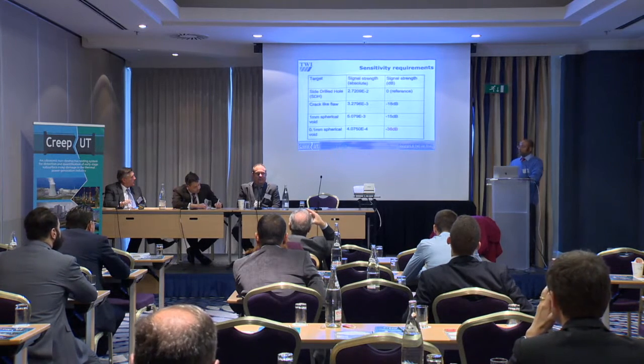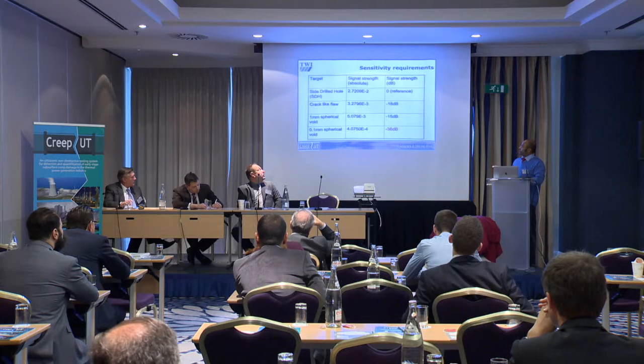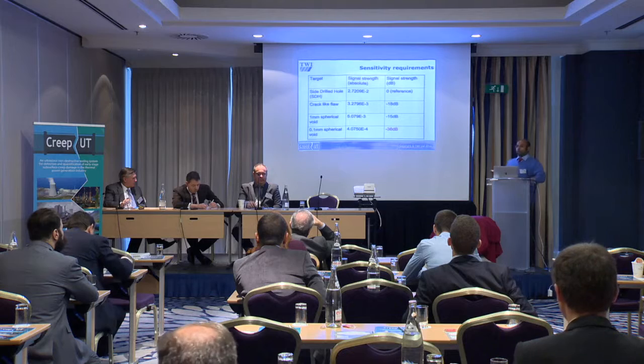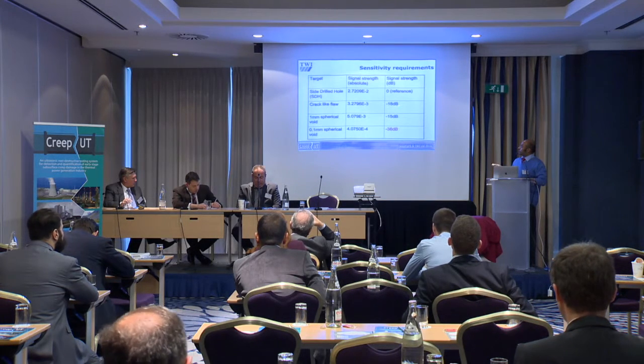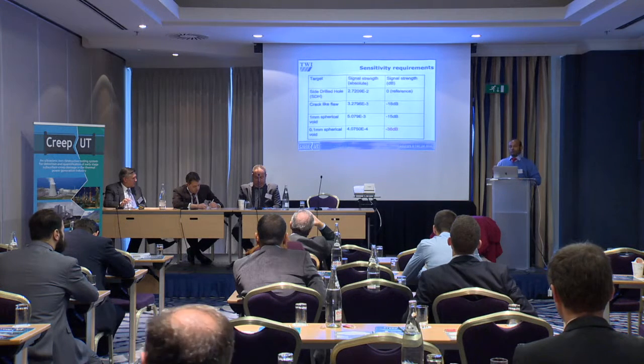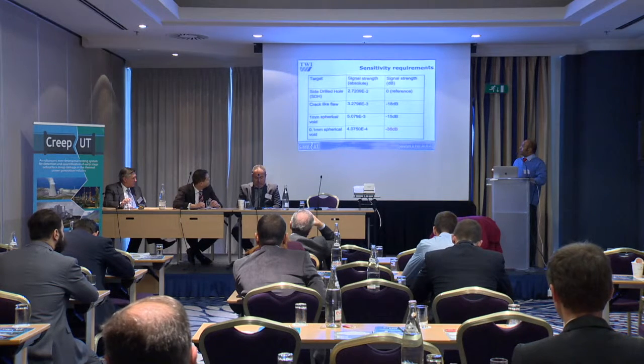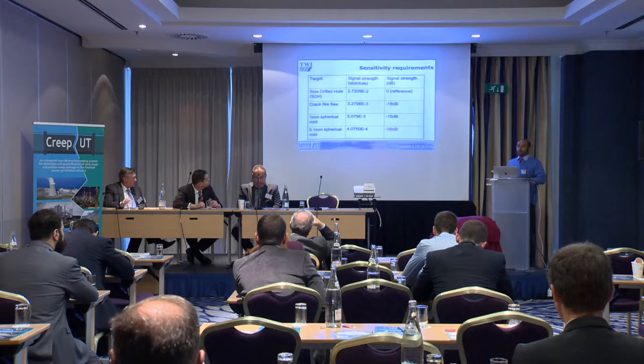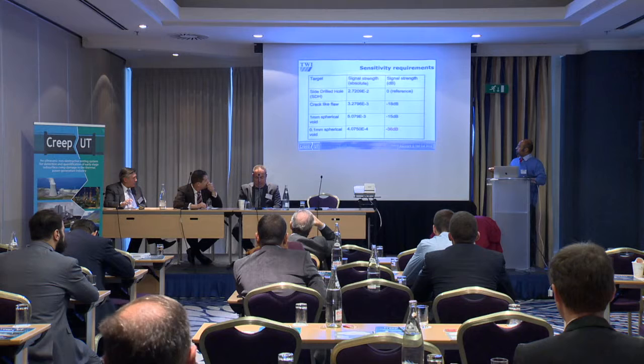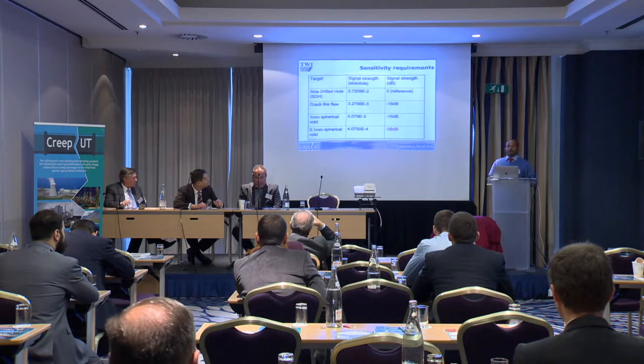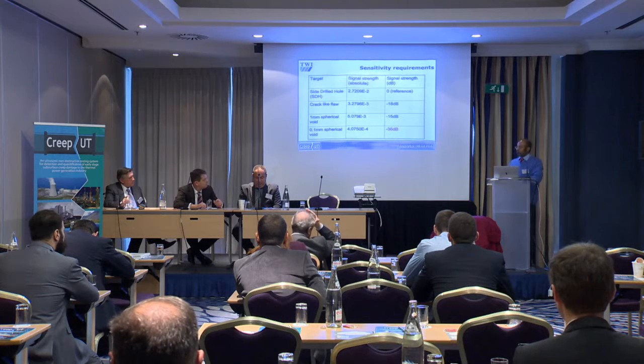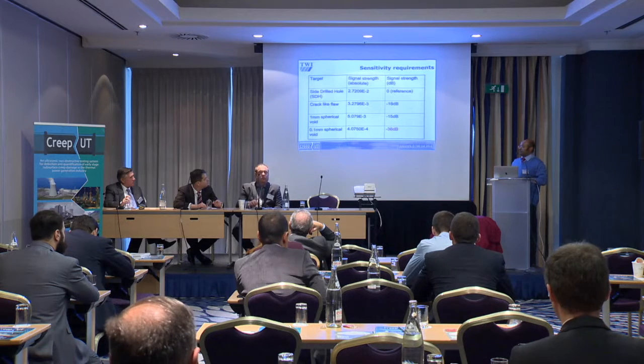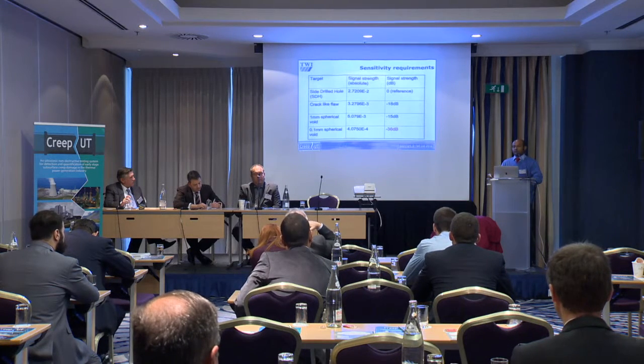And when we did some theoretical assessment at that time, similar to what Marco showed, what you have here is with reference to a standard 3 millimeter side-drilled hole, which is the reference signal. If you look at diffraction from a crack-like flaw, you need to have a system that will be able to give you signal-to-noise performance good enough for something that is 18 decibels below that crack. If you're looking for a 1 millimeter spherical void, such as porosity, then you're looking at 15 decibels down from that. But you can see that if you're looking for a 0.1 millimeter spherical void, which is already 100 micron, which is even larger than the kind of voids, individual voids that you find in a metallurgical structure, you're looking at double what you need for a crack. So that gives you a very good approximate idea of the level of sensitivity that the system requires in order to be able to find creep damage.